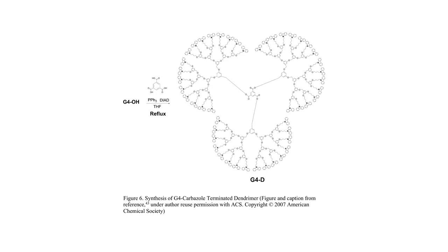They even created double-layered dendrimers with a symmetric core and different functional dendrons, designing materials that could be patterned using light or electricity. This work extended to star-like copolymers, where a dendrimer core initiates the growth of polymer arms, which can then be used for applications like the controlled release of dyes or model drugs from nanosheet films.